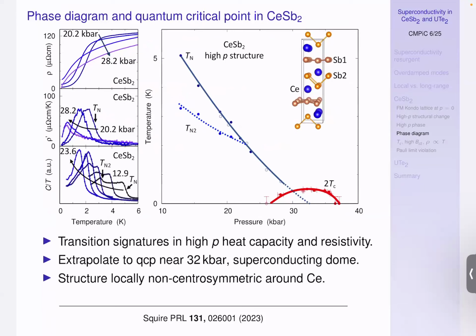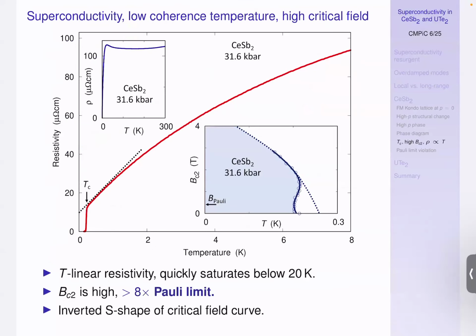So here's the phase diagram, deduced from resistivity but also heat capacity measurements. Basically, this is a magnetic transition which comes down. Then there's a superconducting dome around 30 kilobar. There's probably another magnetic transition, and we haven't yet figured out what that is, but there are two anomalies in the heat capacity. Looking just at that critical pressure, resistivity is linear at very low temperatures, and then it curves over because eventually it saturates. What caught my eye particularly was that the critical field is quite high.